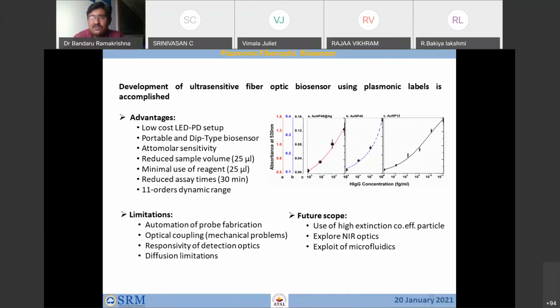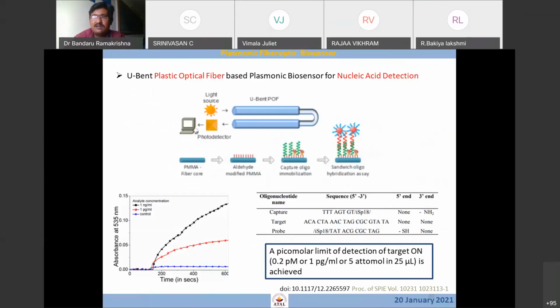And you see the reduced sample volume, almost only 25 microliters of sample is required, and minimal use of reagents. Of course, after that we reduced it to 10 microliters also, but I'm not reporting that here. So the time of your analysis is only 30 minutes. You give your sample, and after 30 minutes collect your report in a very precise manner. Please try to understand, when I say collect the report, very, very low concentrations you can identify. And after that, our colleague has tried a nucleic acid based assay with nanoparticles as